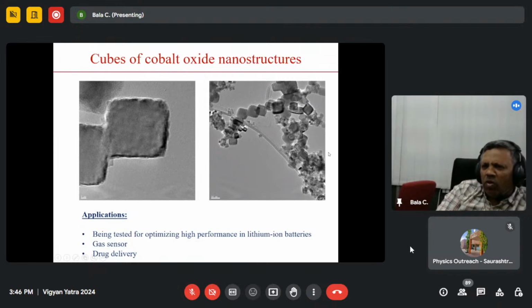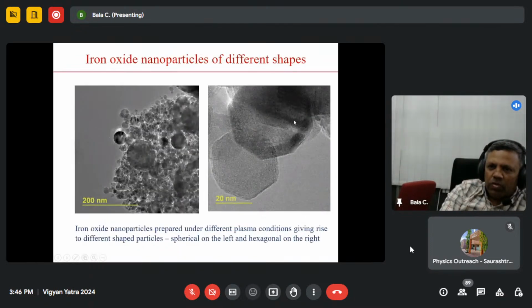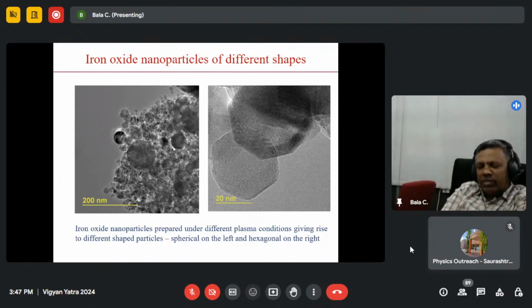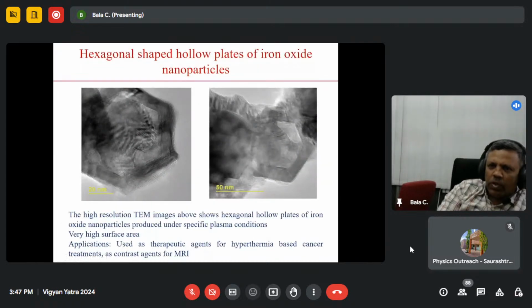We were able to get cobalt oxide nanostructures of cubic shape, quite a lot of cubic shapes, unlike the spherical particles. As you see here with this iron oxide, you can get different shapes and sizes for the same process and the same apparatus, with different materials and different morphological features. You see spherical particles, and in a different process you can get purely hexagonal shapes. You can get plates, hollow plates of the same material,